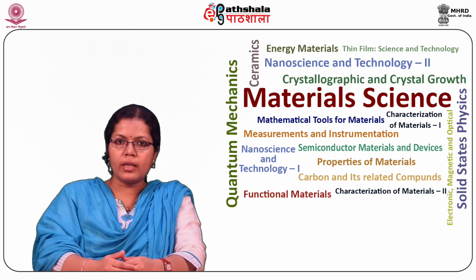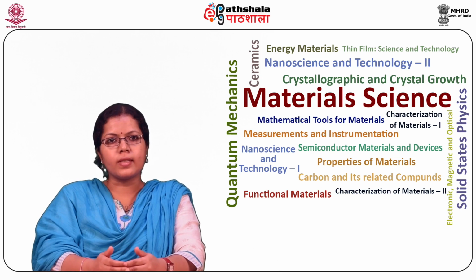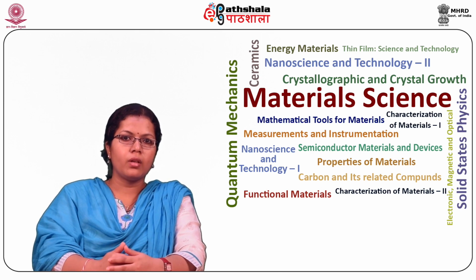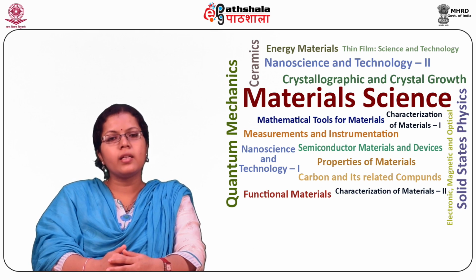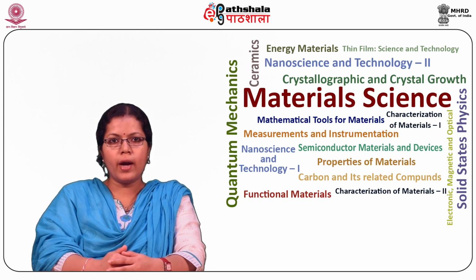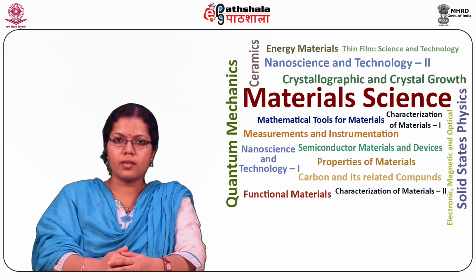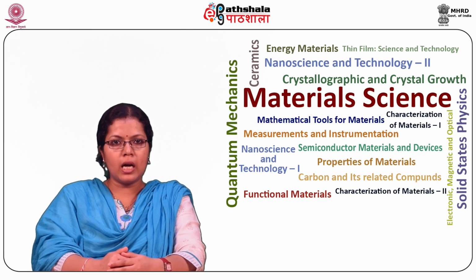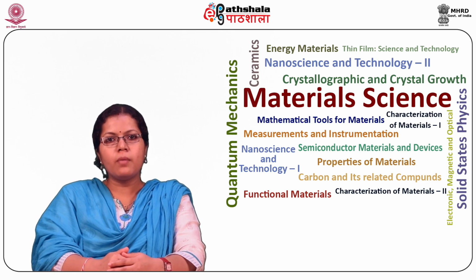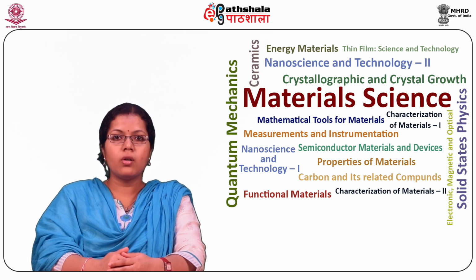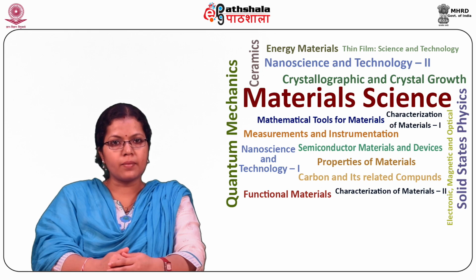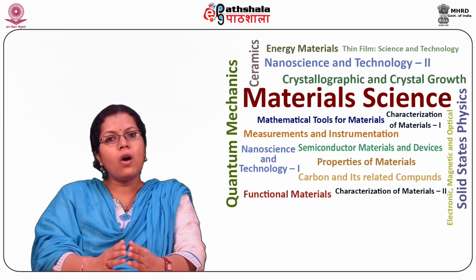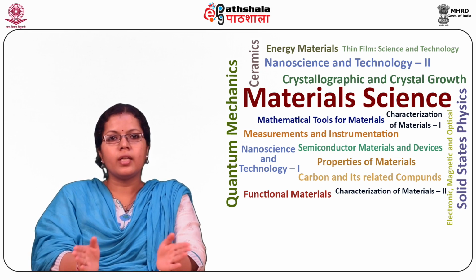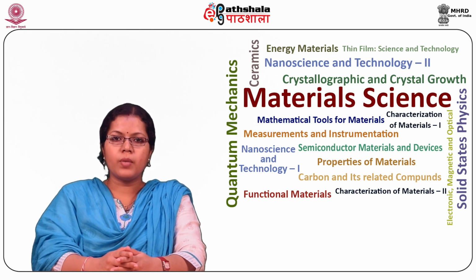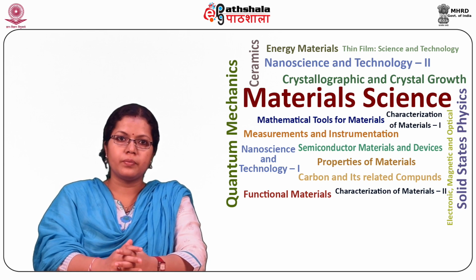The second key component in the synchrotron sources is the monochromator, which is used to select a particular wavelength required for many applications. The monochromators are generally made up of perfect crystals or of epitaxial multilayers and thus allow for considerable variation in the parameters, which may be desirable to choose the wavelength bandwidth.